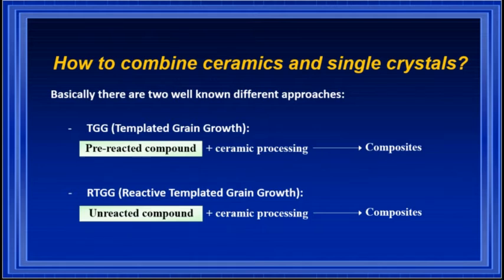How to combine ceramics and single crystals? Basically, we can consider that there are two well-known different approaches. The first one is known as TGG, meaning templated grain growth, where you use a pre-reacted compound and add all the conventional ceramic processing to it to generate the composites. The other one is RTGG, reactive templated grain growth, where you use an unreacted compound and add the same conventional ceramic processing to generate the composites.